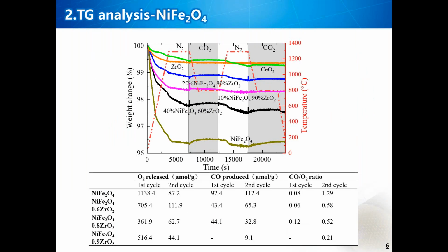And then nickel ferrite is a catalyst that we often use for thermochemical experiments, and it has good stability. At the same time, zirconia is a commonly used carrier for preparing porous materials. Therefore, we chose both to test. The experimental setup parameters are the same as those of the previous cerium oxide. It can be seen from the figure that zirconia has no obvious weight change during the whole process. It can be seen that the stability of the carrier is better.